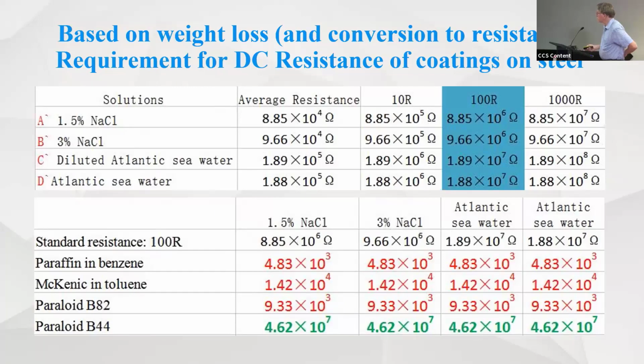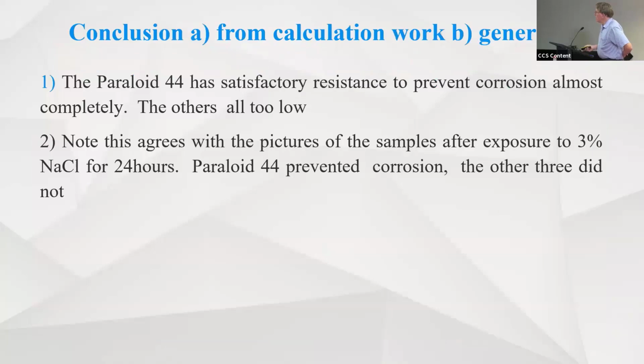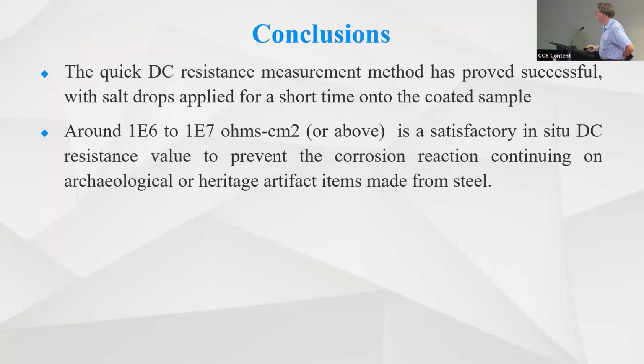This picture is a little complex. This table rather, and relates really to the fact that it does depend on the environment and the type of coating and the application, what your criteria might be. So for this particular example, you might be saying that it's good enough if it's better than 1E6. Not looking at total immersion in seawater, the criteria for good and poor and middling will be slightly different. So the one that came out best was the Paraloid 44. So that bit of work showed the DC resistance measurement as a lab method was working well, and helped the museum decide on the best coating.